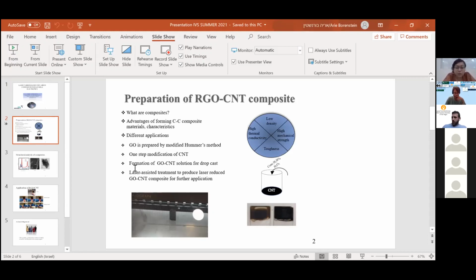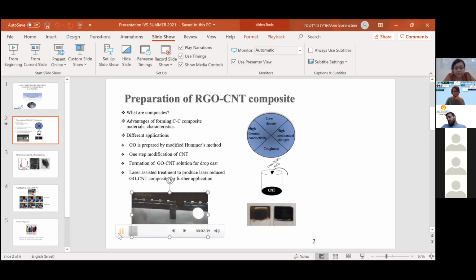So I put one short video to understand how the laser works. Here you can notice the color change from dark brown to black after the laser treatment. The advantage of the laser carbonization over the conventional carbonization is that the laser carbonization takes only a few milliseconds, whereas the conventional carbonization takes hours.